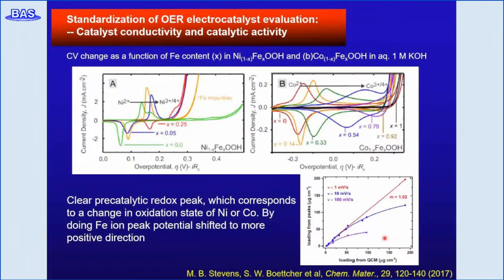This indicates an electroinactive zone exists on the electrode surface. This means kinetically charge or ion transport becomes slow and insulating regions exist on the electrocatalyst.